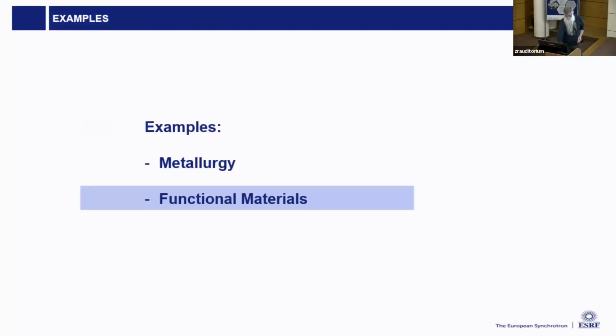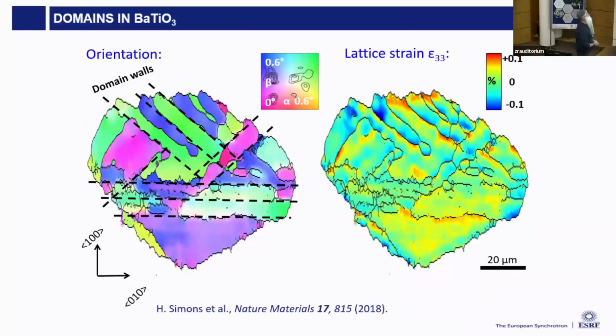The second example is from functional materials. This is a barium titanate, which is a prototypical ferroelectric, where we can see on the left the orientation of the domains, which have slightly different orientations of the lattice planes. And that's the color insert is the angular space. So we can see islands in the angular space. It's basically a reciprocal space map. And these islands correspond to different real space locations of the domains within this grain. And then we can also do strain scans on this, and we can see the strain states within these domains.